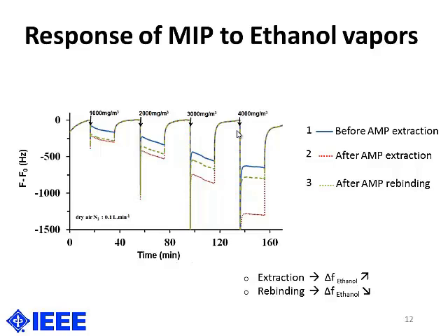The second one in red is after extraction of the MIP, and as expected, of course, we have an increase of the sensitivity due to the presence of specific pores. And finally, the third one is after rebinding of the target compound, and we can see a decrease again of the sensitivity due to the occupancy of specific sites with the template.